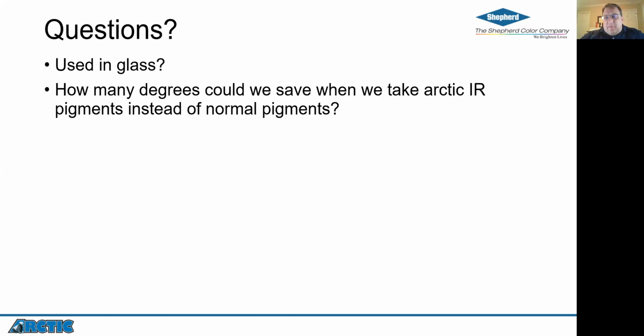So if a standard black is 5% reflective and an Arctic IR pigment is 25%, you've got a delta of 20% reflectance, which should give you about 20 degrees Celsius change. But that would really be about the maximum difference that you could get. That would be for a bright, clear day with very low wind. Usually there's a lot of particulates in the air. That's looking at, I think, over about 1,200 watts per meter of sunlight. So that would be an extreme situation, but that's the theoretical max that you'll get between a standard and an infrared reflective pigment.